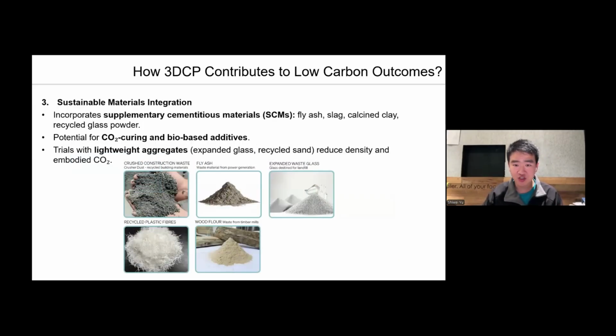Another important contribution of 3D concrete printing is the ability to integrate sustainable materials. In our mixes, we use a range of supplementary cementitious materials like fly ash, slag, calcined clay, and even recycled glass powder. This not only reduces cement demand, but also improves pumpability and helps us control the cycling time. On the printing side, we also recycle our own concrete waste, sending it to a local crushing station to produce crusher dust, which we can then reuse in our future jobs. This creates a local circular material loop.